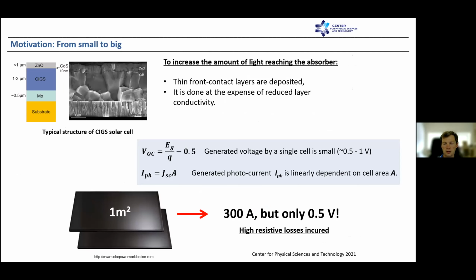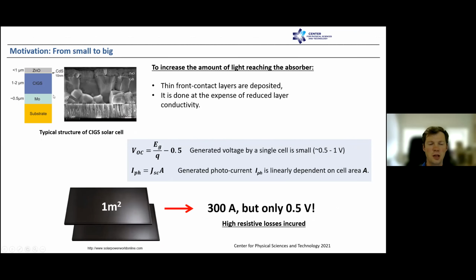So where do we need to use lasers in such devices? Here is a CIGS structure. We have a substrate, which could be glass or, let's say, a flexible polymer substrate. You have a molybdenum back contact, an absorber layer, and a thin transparent conductive oxide, for example zinc oxide. You see that the layers are quite thin.